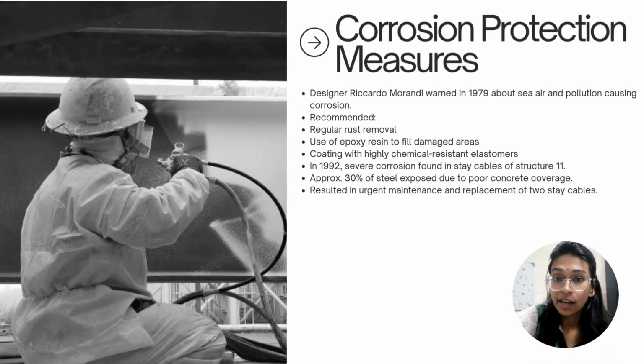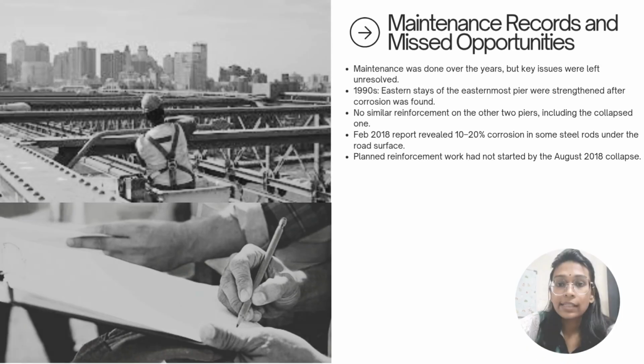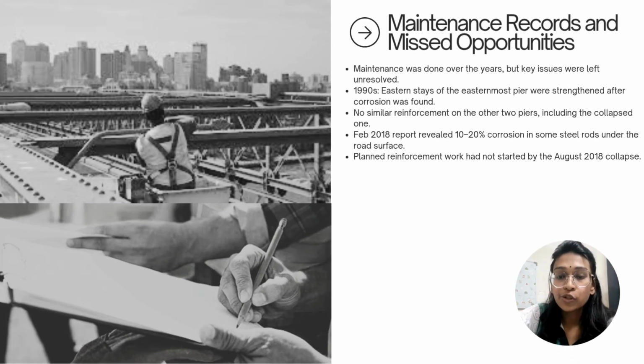Back in 1979, designer Riccardo Morandi warned that sea, air, and pollutants can cause corrosion. He recommended regular rust removal, filling damaged areas with epoxy resin, and coating with chemical-resistant elastomer. However, by 1992, severe corrosion was found in the stay cable of structure 11. About 30% of the steel was exposed due to poor concrete coverage. This led to urgent maintenance and the replacement of two stay cables. While maintenance was performed over the years, critical issues remained unresolved.